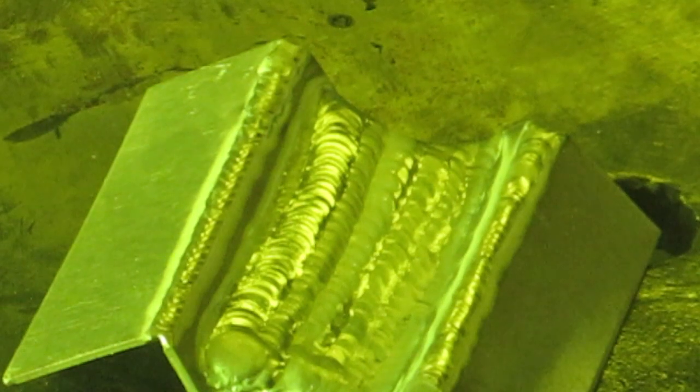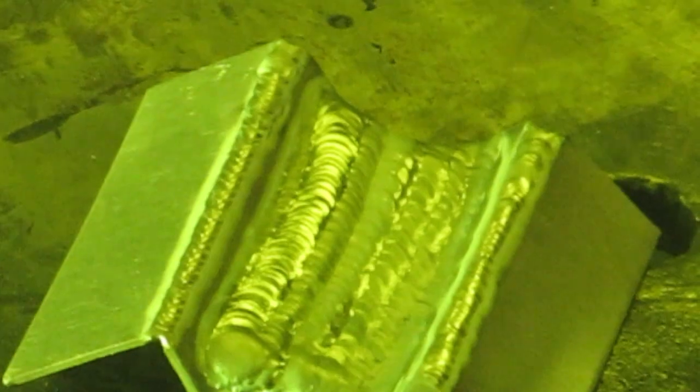Last thing I want to mention as we come to the termination of the weld is that you'll notice that at the very end of an aluminum weld, it's very important to add a little extra filler metal and to ease off on the pedal, ease off on the amperage. Because if not, you don't add that extra filler metal and you don't ease off gently, you'll end up with a little crater at the end which will result in cracking.